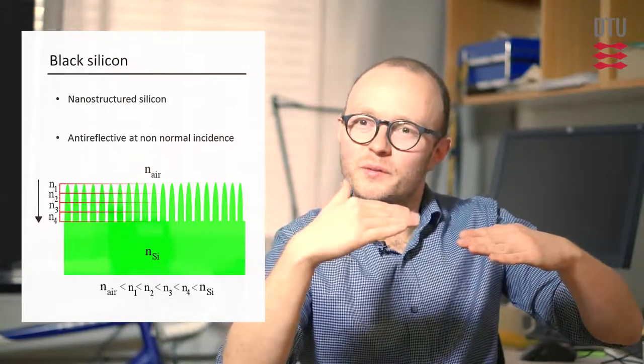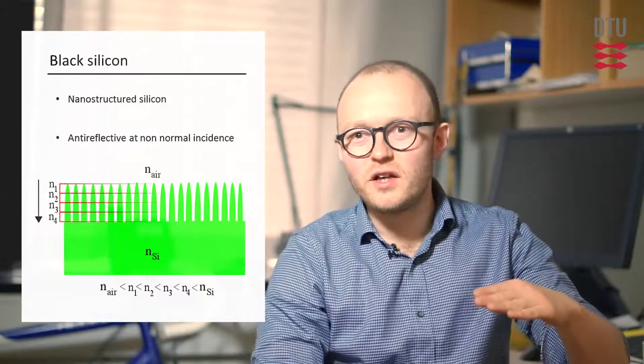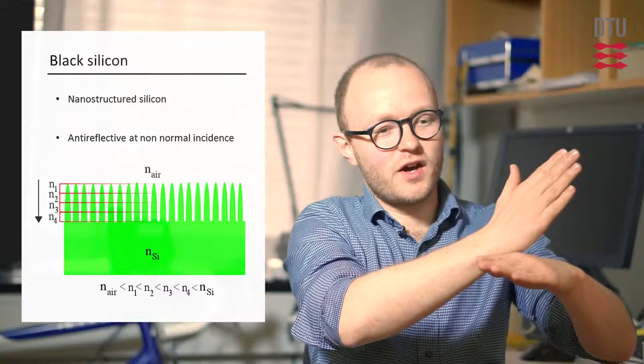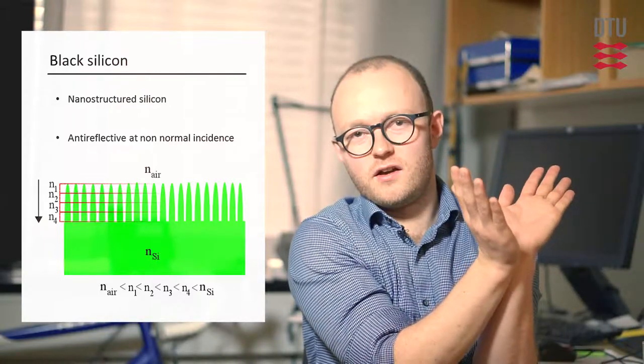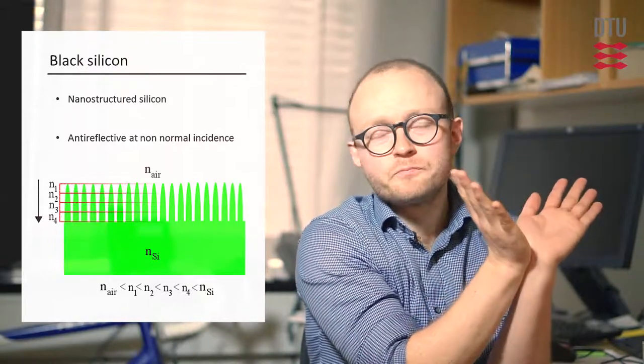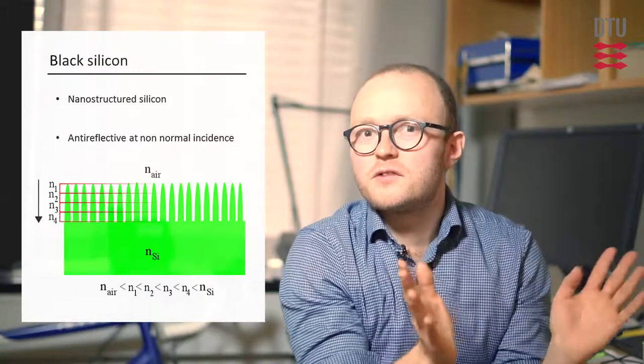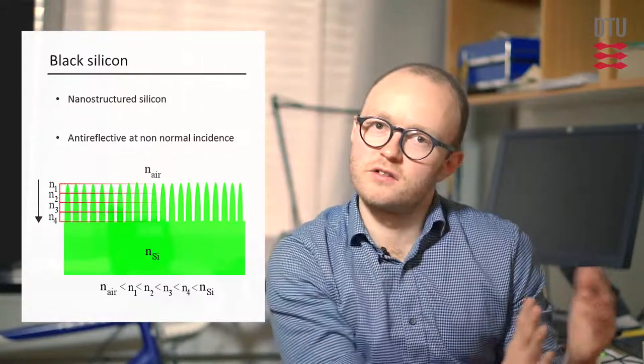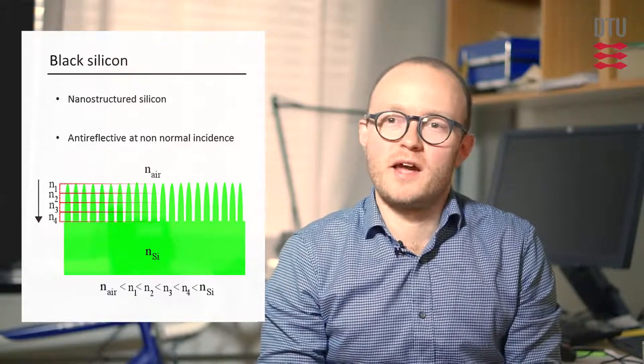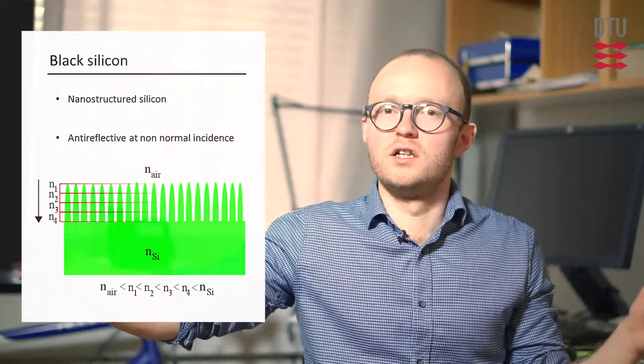At some point, we reach the Brewster angle where we have reflection, high reflection, also on black silicon. But there is a broad range of incident angles in our studies, up to say 45-50 degrees from normal on both sides, where the reflection remains below 1%, so where the cell still looks black. And this is a feature that we hope to be able to benefit from in future black silicon solar cells, but it's important to test it on full scale in real panels.